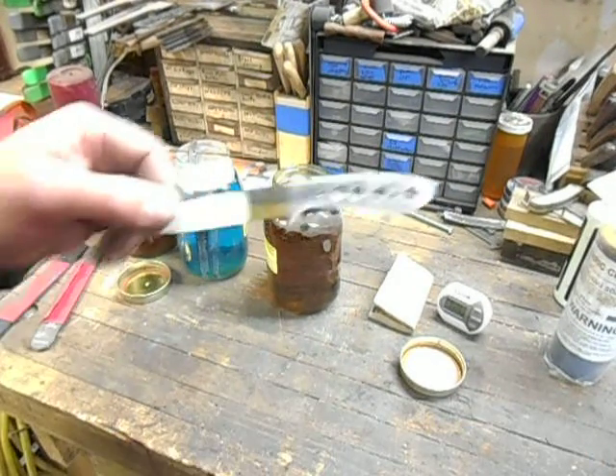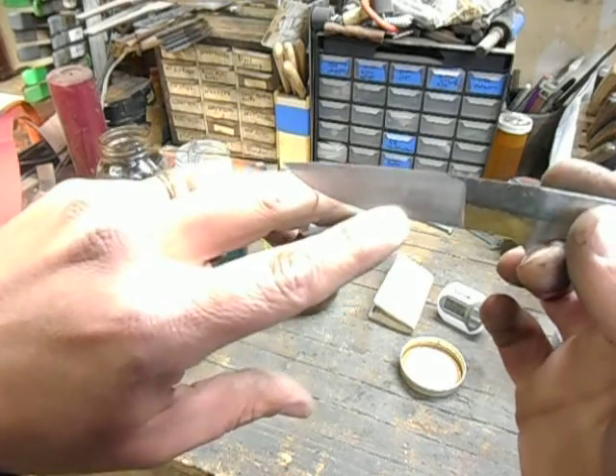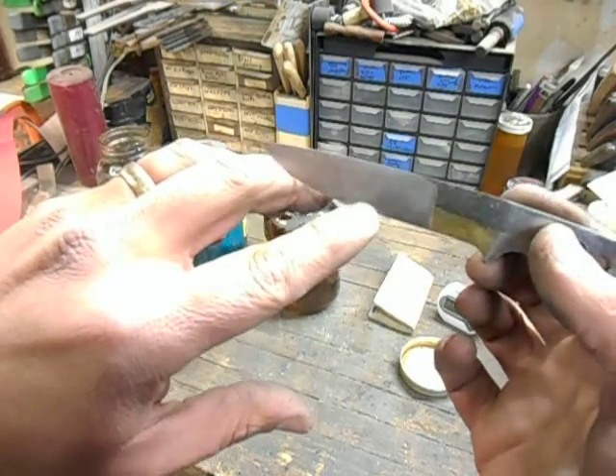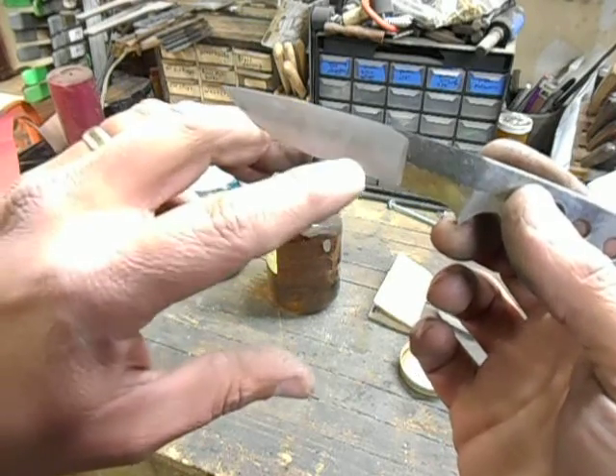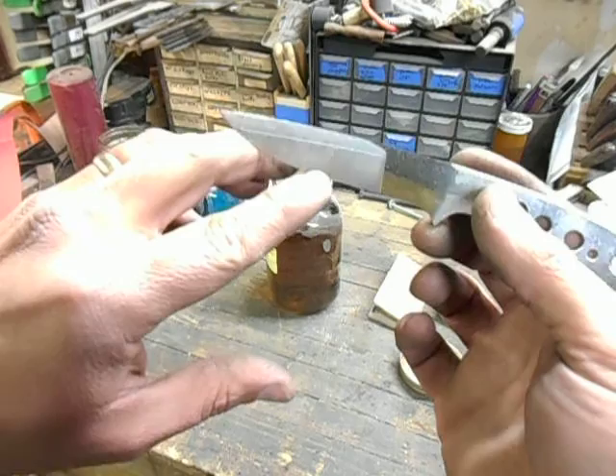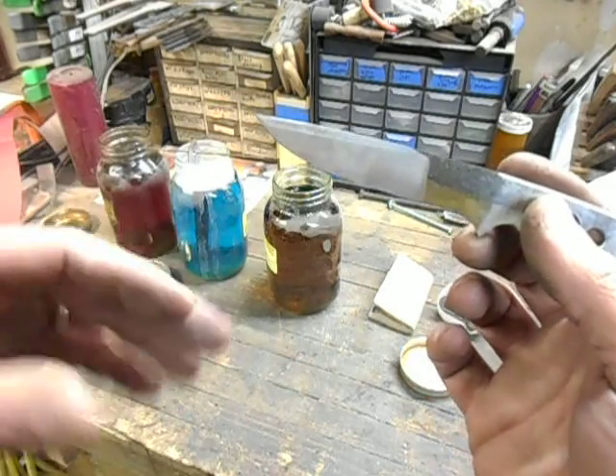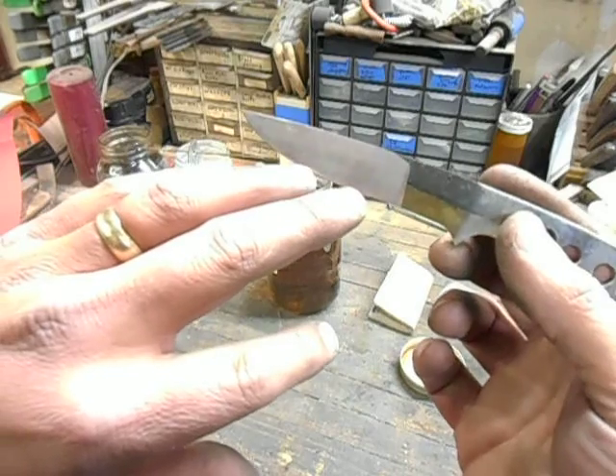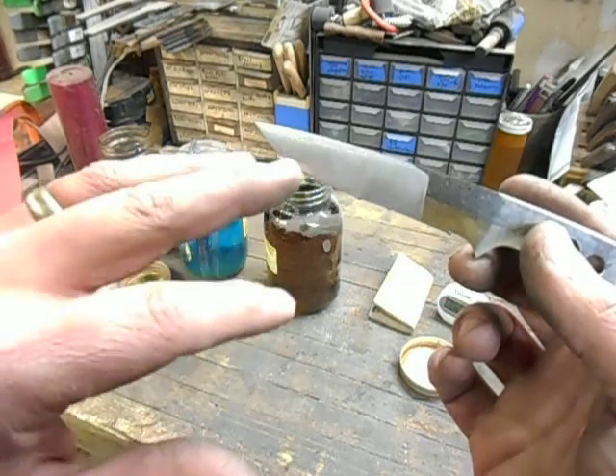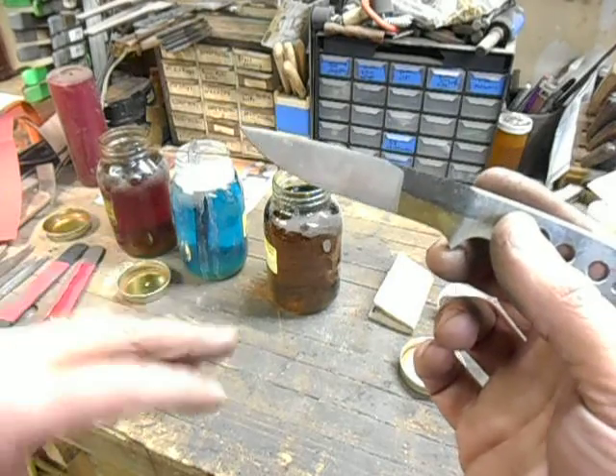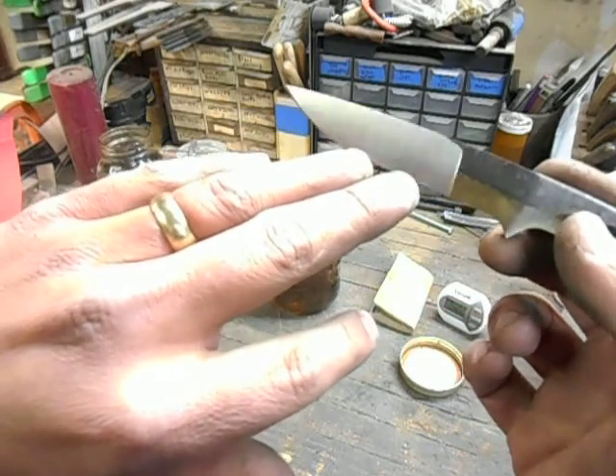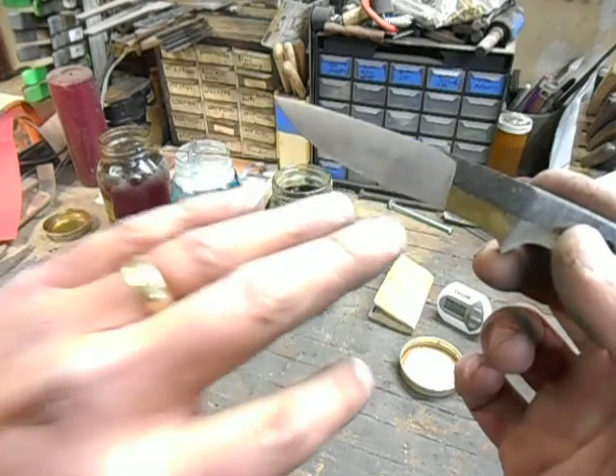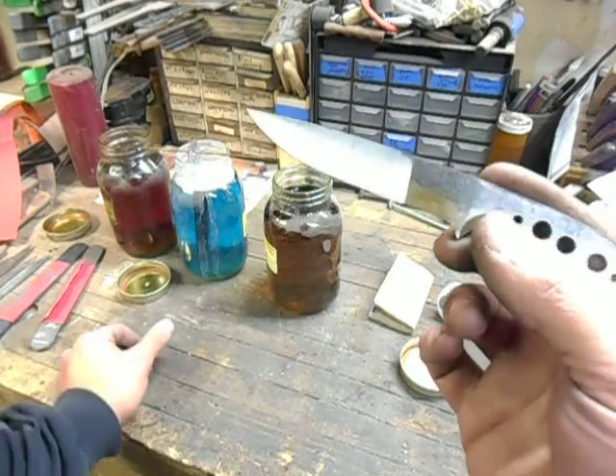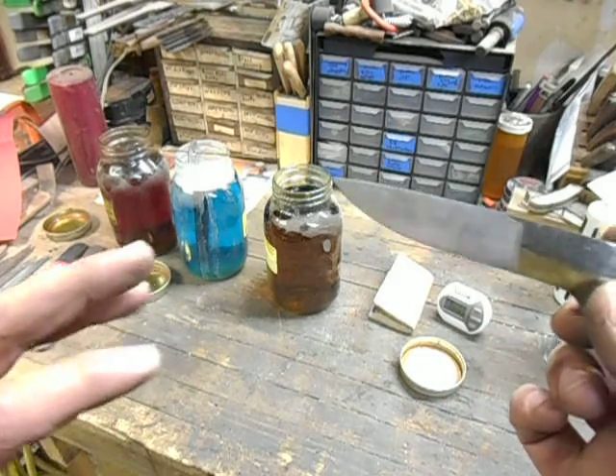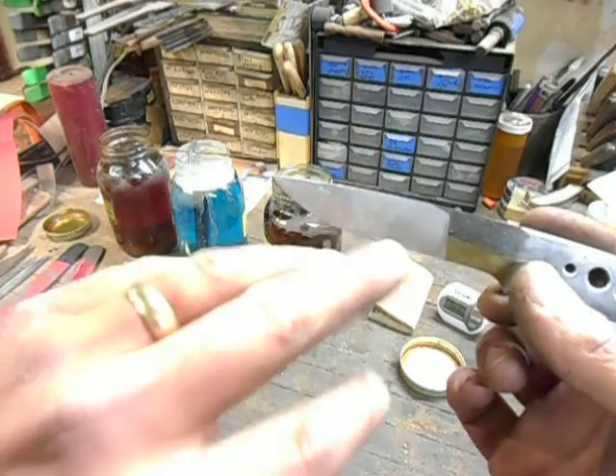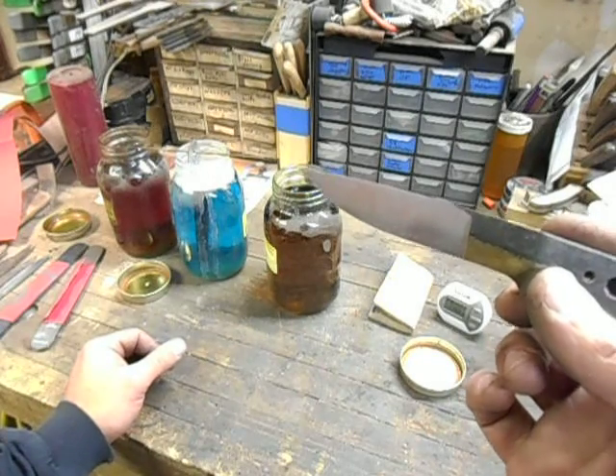So anyway, this blade right here, if while you were grinding it you got a color change on this steel, usually it'll happen near the edge where the edge will turn blue. Well, it can turn all kinds of colors, from just a slight yellow all the way up through dark brown, blue, purple, and then go back to silver. Those are oxides that'll tell you the temperature that steel reached when it got overheated. Okay, well, it's real simple to take. If you're not a very scrupulous knife maker, let's say you turn part of that edge blue while you're grinding it. Well,